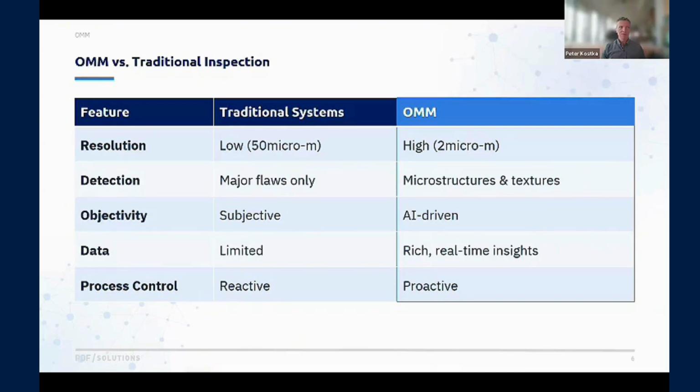The downside of all of this, of course, there's always a downside, is because the resolution is so high and the data volume is so high, we can't do 100% inspection. We do statistical inspection, which means if you're looking for like a 1 in a trillion fault, we're not going to catch it. But if you're looking for a 1 in a billion kind of fault, we're more than able to catch it. It'll just take us, I think, something like an hour to capture most relevant PPB kind of failures.